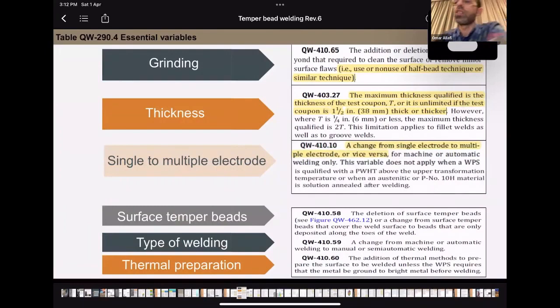Single or multi-pass is a change from single electrode to multiple electrode or vice versa. When you change, you need requalification. Surface temper bead: the deletion of surface temper bead, or a change from surface temper bead that covers the full surface to that only deposited along the toes of the weld. Sometimes the temper bead is placed over the full surface of the weld, or sometimes it is placed near the toes of the weld to temper the heat affected zone in this area. If you are qualifying using surface temper bead for the full weld, you cannot change it to beads only deposited along the toes without requalification. In this case, requalification is required.